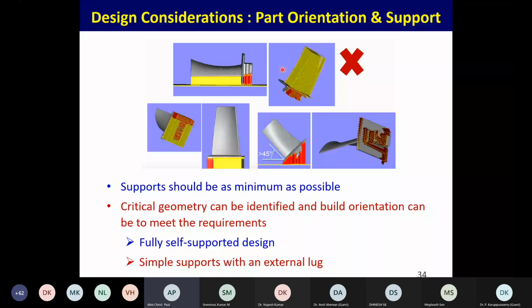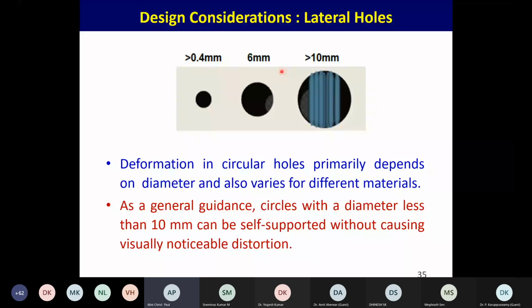Similarly, if you want to make lateral structures, the diameter of the hole can be 0.4 millimeter, 6 millimeter, or 10 millimeter. Whenever you are crossing the diameter of 10 millimeter, you need to have supporting structures, otherwise this will not stand there in case of the metal. Now, how to remove these support structures during the finishing operation is again an issue. So we have to spend time designing this.